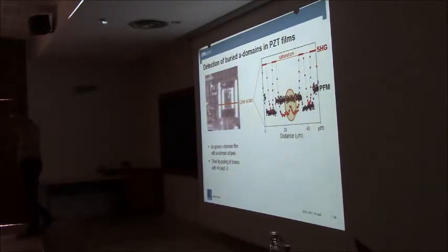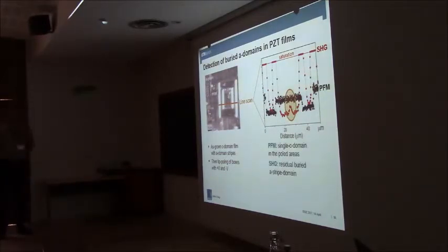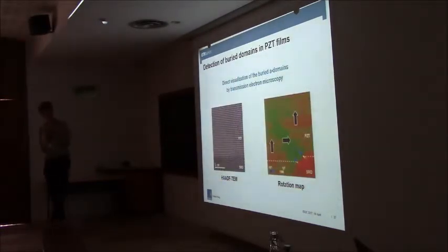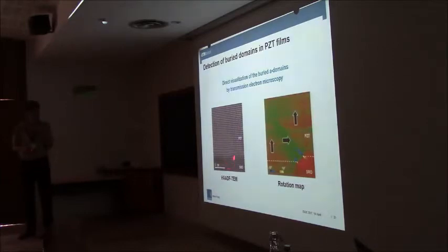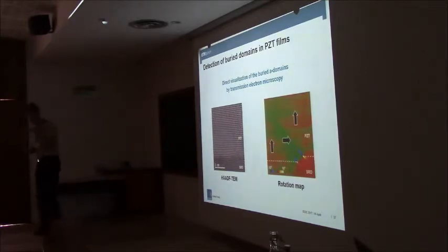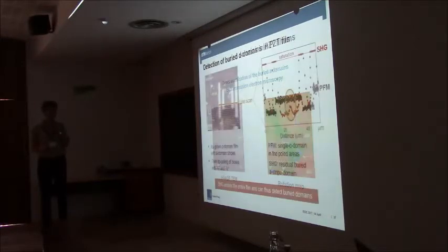And in order to verify that this is really the case, we did some scans by transmission electron microscopy. And indeed, when you go to the bottom of the PZT, where it connects to the strontium ruthenate, you see there is an A domain. Not visible to piezo response force microscopy, but visible to second harmonic generation. It's pinned to the interface. And therefore it's buried in the film. But here you can see it, and also optically you could see it.